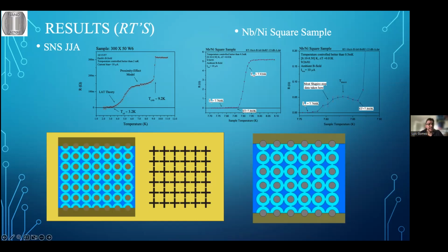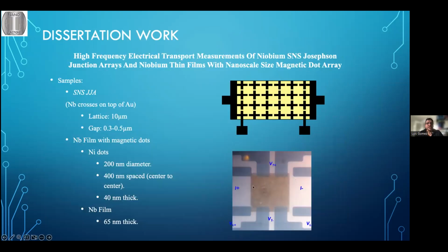So basically, first you put the big square, it has the nickel inside there, then you put the film on top, the niobium, and then you remove this part with photolithography. And then you make the electrodes. To these ones you send the current, and to this bottom one you measure voltage, longitudinal voltage from this side to that side, or you can also measure the transverse voltage across the sample this way.